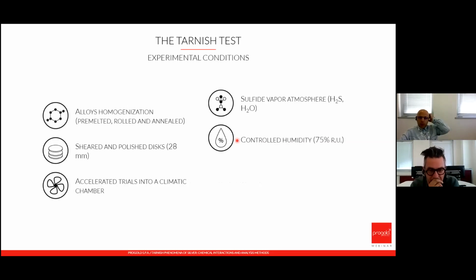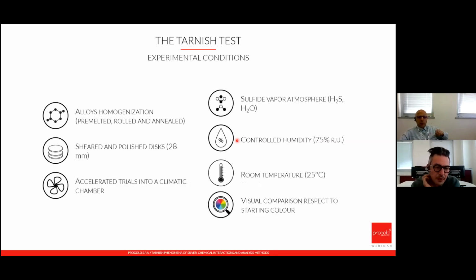Currently, the homogenized sterling undergoes an accelerated test, being surrounded by a hydrogen sulfide atmosphere produced from the floor by vaporization of a very dilute ammonium sulfide solution, with controlled conditions of temperature and humidity inside a climatic box.